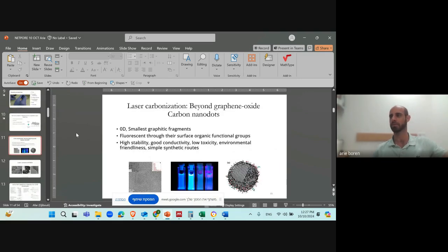And one of the materials that I like very much is carbon nanodots. And this is also Volker's idea. And the reason is that carbon nanodots are probably the smallest graphitic allotropes. They have a very special structure where in the core they have graphitic structure, sp2 carbon. It's a little amorphous sp2 carbon, but on the surface they are coated with functional groups. You can see here a TEM of the nanodots, very small, down to maybe 2 nanometers, very easy to produce.